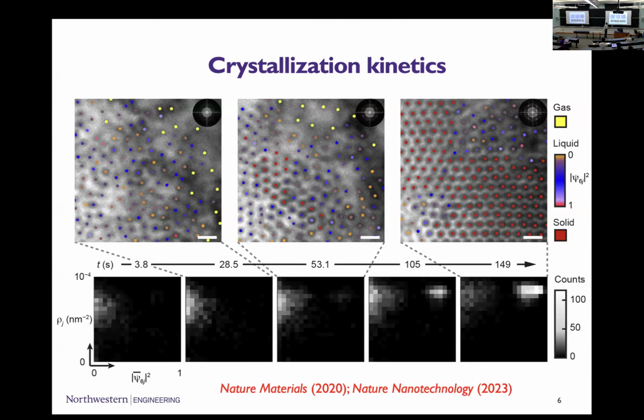What's cool here, if you look at the bottom row, you see that there is an x and a y-axis. The x-axis is the order parameter in terms of hexagonal packing. The y-axis is the density. So what we find is, and every system, the images look like this, right? You say, oh, they look kind of fuzzy. This is on purpose. It is very easy to get tempted into getting beautiful TEM images by cranking up the electron beam intensity. Sure, it looks great, but it fails within no time because you're creating so much salt. And then you change the interaction between the particles.